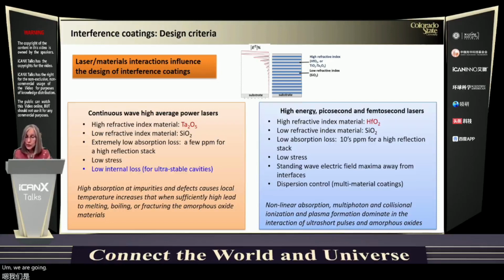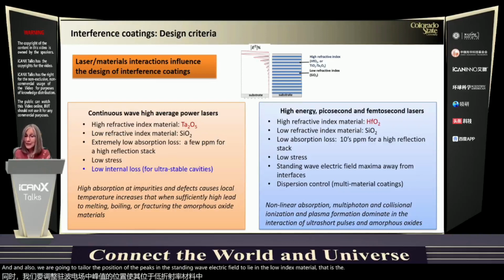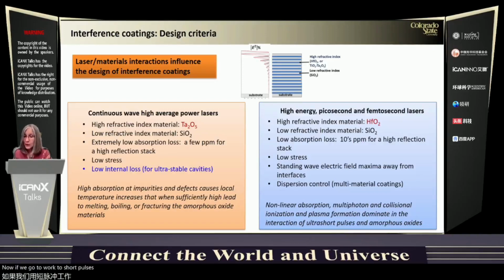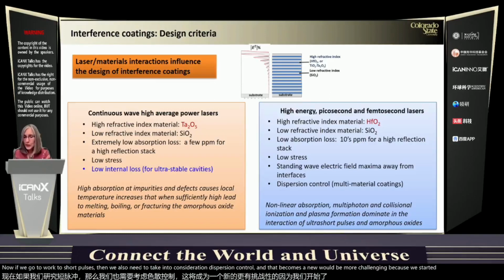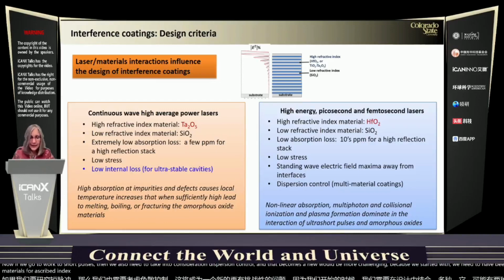We are going to require that the coating has low stress, and also we are going to tailor the position of the peaks in the standing wave electric field to lie in the low index material that is the most robust to laser damage. Now, if we go to ultra short pulses, then we also need to take into consideration dispersion control. And that becomes a little bit more challenging because we need to then incorporate in the design multiple, probably 2 materials for the high index layers instead of just 1.